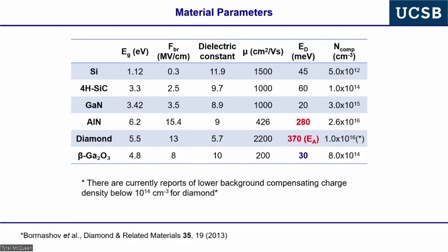Okay, and many semiconductors have dopants that are absolutely hydrogenic. This is hydrogenic. This is hydrogenic. It's higher than this because you have a low dielectric constant in silicon. It just falls out beautifully. But many don't. Okay, and aluminum nitride doesn't, and diamond definitely doesn't. And one of the sites in gallium oxide is hydrogenic, and one is not hydrogenic. Yeah. We don't know. And so Chris Van de Walle and I have a big fight on this.